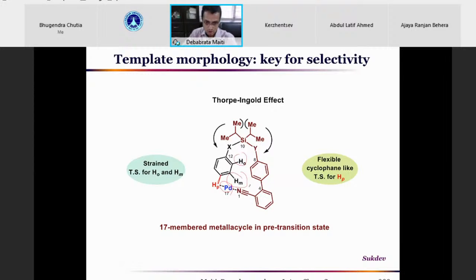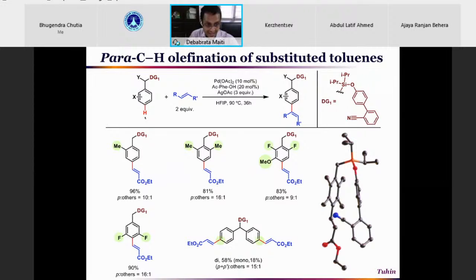So that's the power of organometallic chemistry or this directing group approach for this sort of reaction. So in this case, for example, we are able to promote the olefination selectively at the para position. So we see that selective olefination can be done at the para position. This is the crystal structure showing clearly that from the organic substrate, the template is coming and wrapping it up so that olefination can be done at the para position.